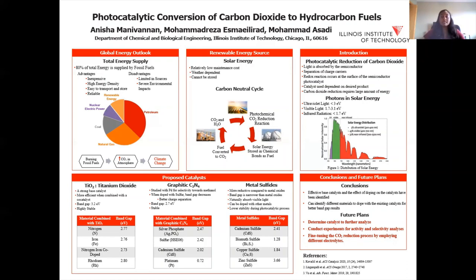Band gap is the energy between the highest occupied molecular orbital and the lowest unoccupied molecular orbital. Band gap is a really important way to distinguish between different catalysts. Catalysts can be doped with other materials to tune the band gap to the desired range. Titanium dioxide is a strong, highly stable catalyst, which has a higher band gap of 3.2 electron volts, so is more efficient when combined with another catalyst.